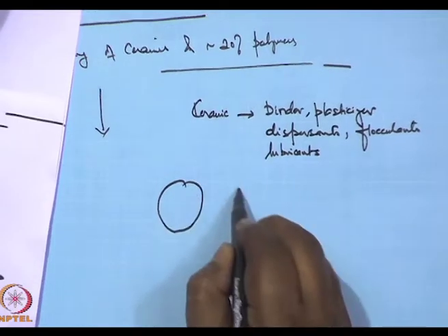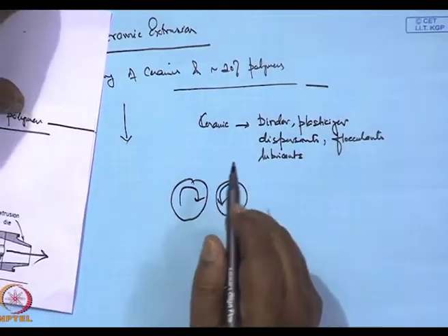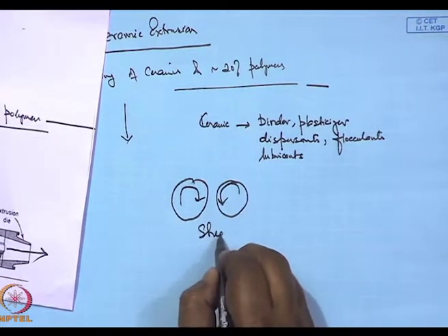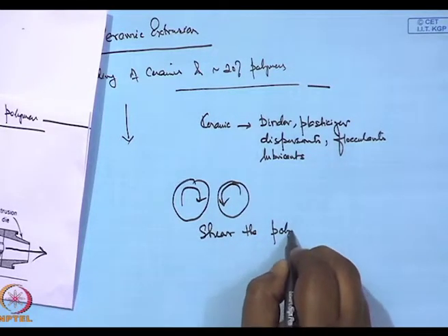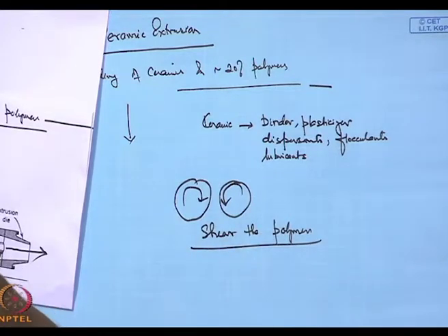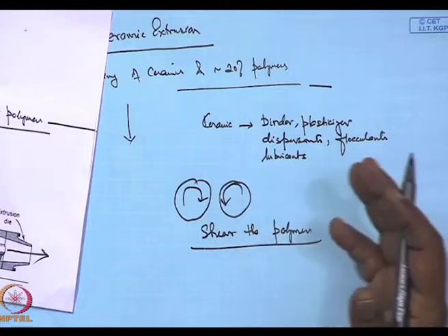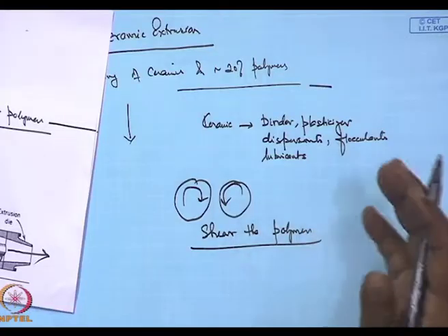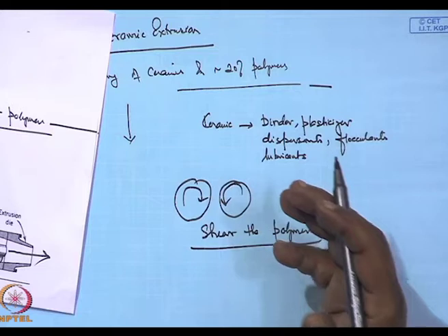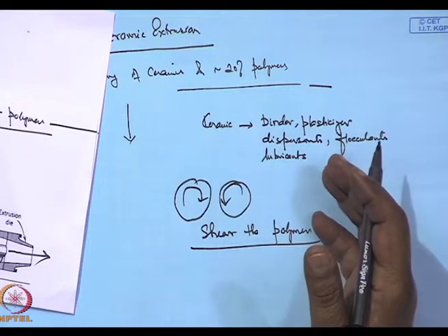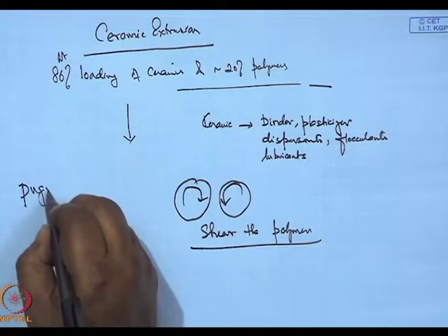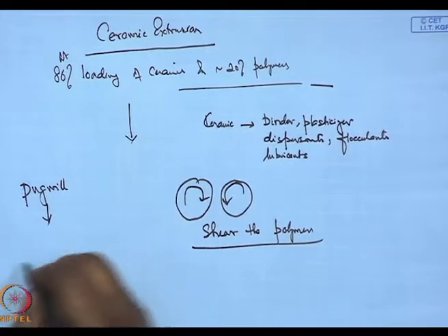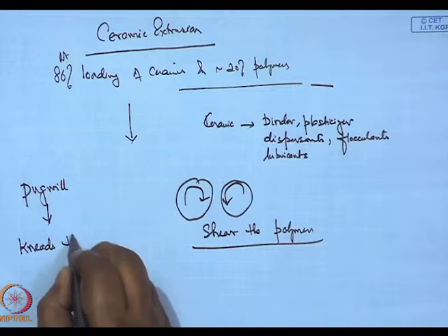This is added to this pug mill, where counterclockwise rotating blades shear the polymer, as you saw in the first video, mixing the plasticizer helping in the shearing, the dispersant, flocculants and the lubricants dissolving in that molten polymer, the ceramic powders being coated with the dispersants and the flocculants, and the pug mill. What does this do? It makes the premix.